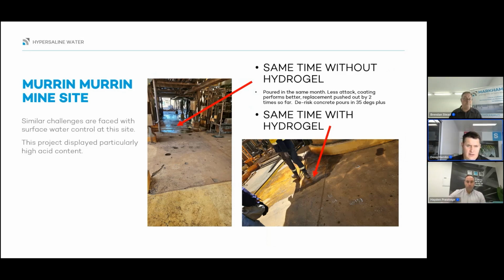So the last project we want to have a look at here was the Murrin Murrin mine site. This is a very unique site. It has some very harsh conditions, obviously hot, dry and windy, and the processing plant there has some very aggressive chemicals, shall we say. What they were finding is that the damage you can see on the left, the pitting and cracking, the gouging out along that crack, was happening at around the 18-month to 2-year period, and it wasn't long from there that they would have to be breaking that concrete out and replacing it, as they were bunded areas. They needed protection from those chemicals getting into the ground.